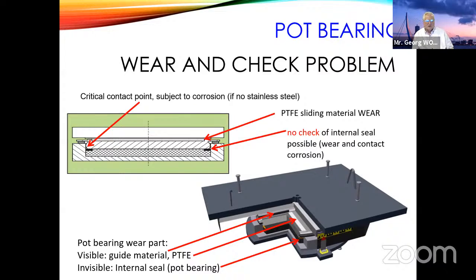And of course, you could also do something against it by using stainless steel. So for around 8 years in Singapore, for example, only pot bearings made from stainless steel are allowed, but that's really incredibly costly. And still there is the problem that you have no check of the seal. You just have to trust that with stainless steel you have no corrosion. And on top, we have the PTFE sliding, and here, in the long term, we have seen a lot of wear. Especially endangered are steel bridges, because they have more movement than concrete bridges, and this causes the wear. And of course, also railway bridges. I will come to that later.